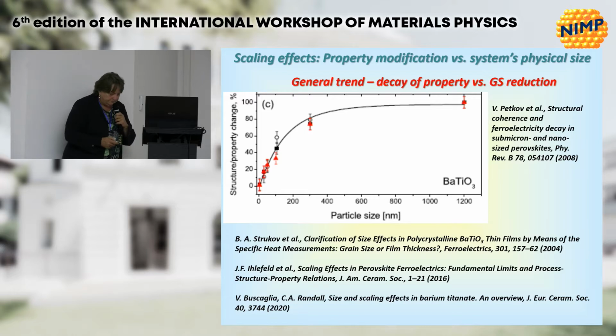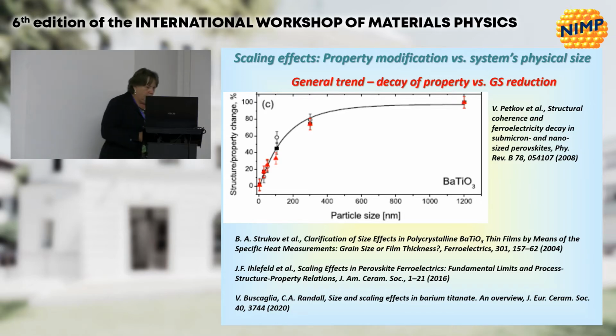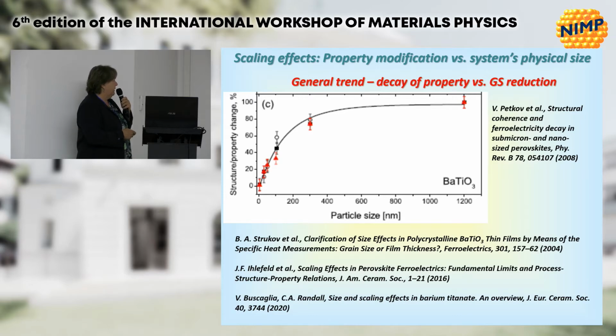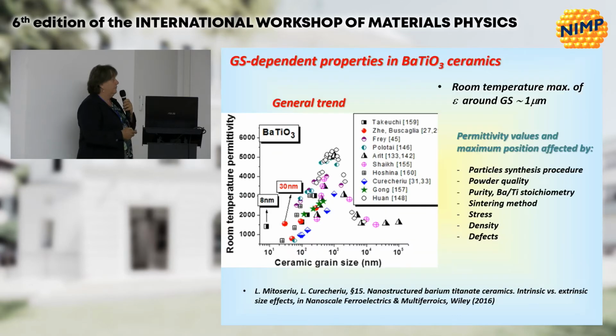Well, typically when you reduce the size of the system, irrespective of whether it is film thickness, grain size or particle size, almost all the properties scale, they show a decay, like this one. Here the spontaneous polarization has a decay, and so do tetragonality and other parameters, with the exception of the dielectric constant.